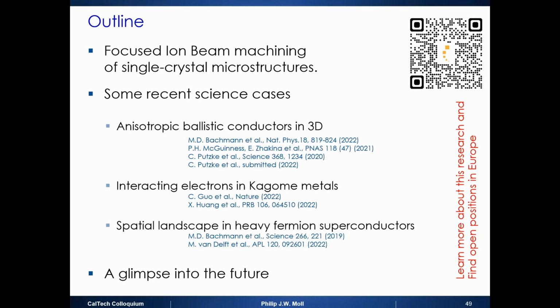Some are hard. Cuprates, for example, are very hard. Because if you cut cuprates, you get a thermal gradient. And the thermal gradient leads to gradient diffusion of oxygen. So you end up with an oxygen-depleted surface after the cutting. So this was very hard. We've fixed this problem now with going to a cryogenic stage. So you have to cool the system down to 70 Kelvin so that even under fabrication conditions, you keep it below the mobility edge of oxygen, and then you freeze it back in. It's one way. Other thing is we could re-anneal things.